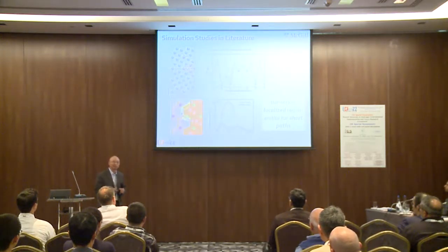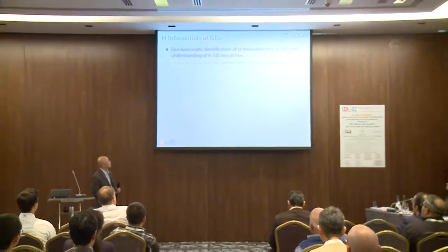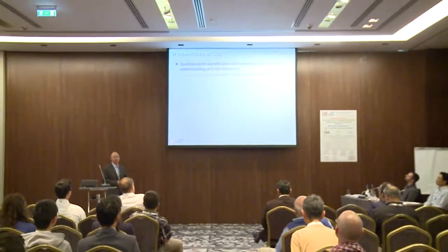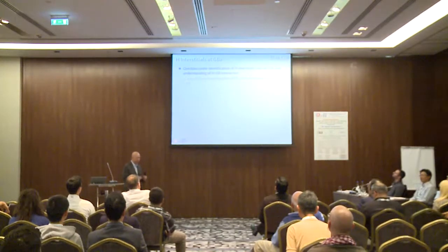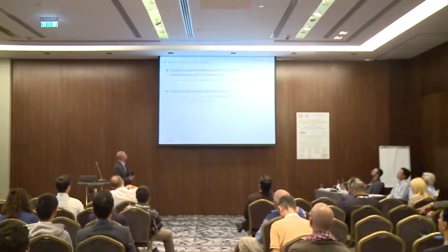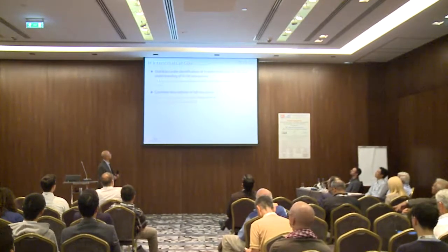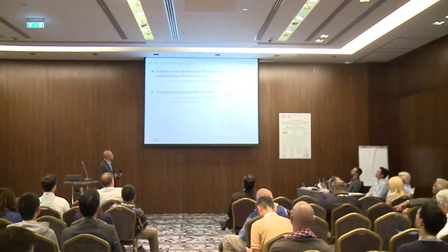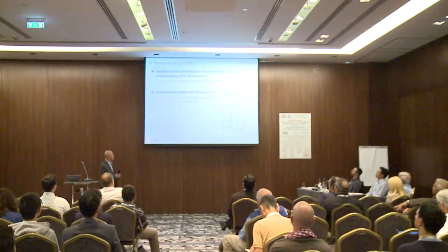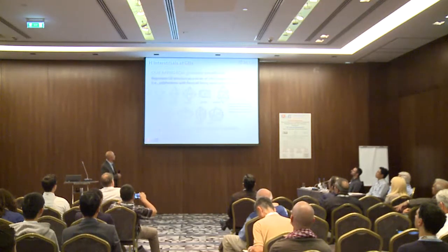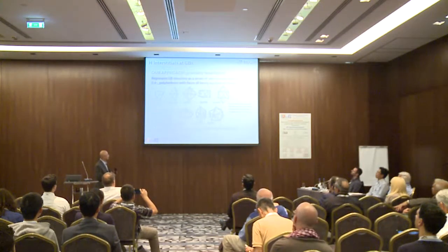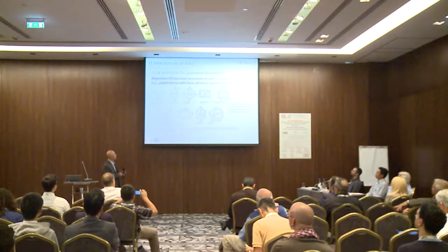So we try to really see, okay, what's the exact role of grain boundaries? And for that, of course, first we need to have effective tools to analyze the grain boundary structure. So the tool we're using is based on the polyhedron rather than the common CSL method. So we use this 3D polyhedron method to describe grain boundaries. So just keep the story short.